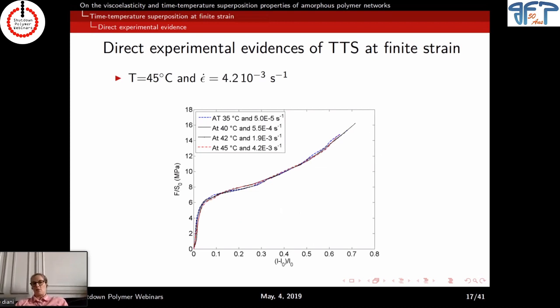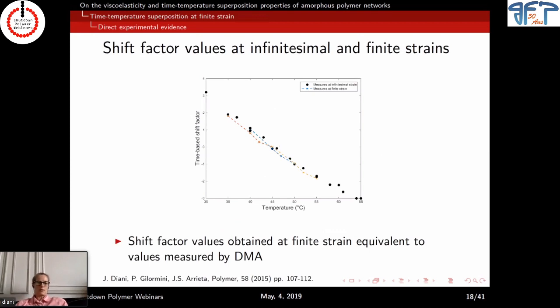So now that we observe time temperature superposition at finite strain, we compared the shift factor measured in the linear regime with the DMA test, and the shift factor measured at finite strain with the stress strain response in uniaxial tension. And as you can see, they are completely equivalent. The limit of what you just saw is that we were not able to prove that when the material was in the glassy state. The material was either in the rubbery state or within the viscoelastic transition. The problem with the glassy state is that we would have needed to run tests at high strain rate with a good accuracy, which we weren't able to.